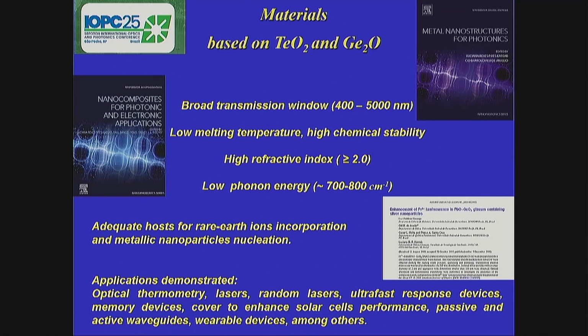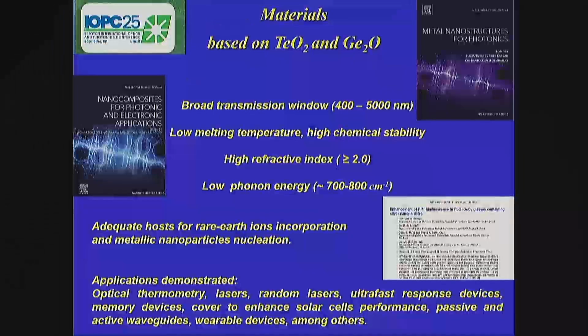In fact, around 20 years ago, we demonstrated in this paper from Applied Physics Letters, the first demonstration of nucleating metallic nanoparticles, silver nanoparticles, in germanate glass, and at the time we could show the improvement of the optical properties of praseodymium ions. Since then, we have investigated these plasmonic effects in different situations. And more recently, we also showed the possibility of creating nanoclusters, silver nanoclusters, in the same host.